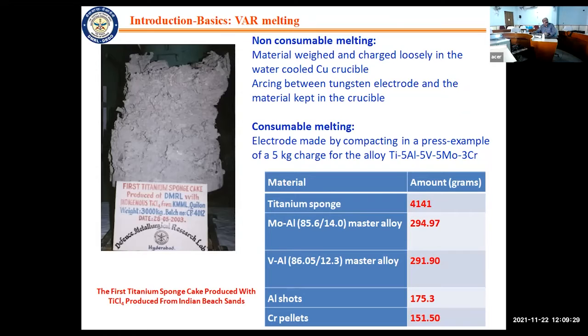So they tend to segregate. So that is why they are added in forms of master alloys, aluminium based master alloys. Okay, so these are all imported. India does not make these aluminium based master alloys. Only iron based master alloys, which are very much required by steel industry, is melted and processed. So you add these master alloys, that brings down the melting point as well as the density, so the mixing is proper, and then you add aluminium shots and chromium pellets. So this is the typical charge for, let's say, if I want to melt a Ti-5553 alloy. So you can multiply depending on the